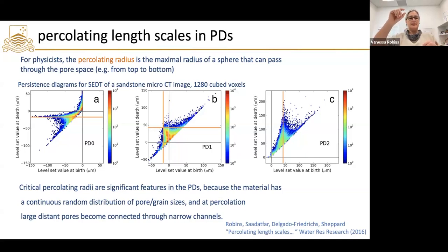And then as we get to this critical radius, we can suddenly connect the pore space across the full image domain. And that means we're now able to join the very largest pores from two previously disconnected components via what must have been a relatively very narrow throat. Okay, so that's why we're seeing this signature of percolation here.